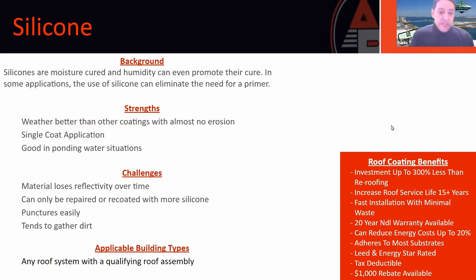There are limitations with using the silicone. Two of the big ones are that once you put silicone down, you cannot coat over it with anything else but silicone. Nothing else will stick to it. So if you do a repair with silicone, you're going to end up with a situation where you either have to scrape off the silicone or recoat over the silicone with silicone.